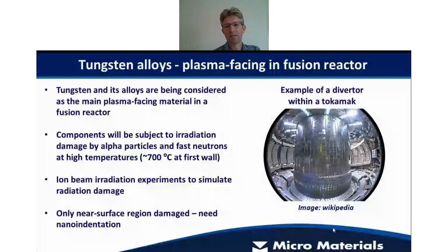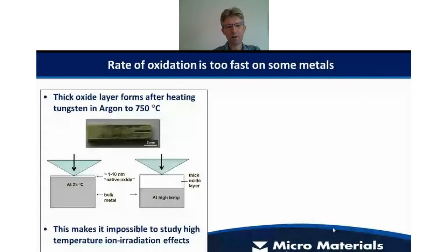So one particular application of this, and it's particularly timely now, since Tuesday the construction started on the ITER fusion reactor in the south of France, and tungsten has been used in these as a plasma facing material. And in this application, the tungsten components are subjected to irradiation damage, and a lot of research is based around trying to simulate that type of damage with ion beams. And in this case, the samples are not radioactive. The damage is restricted to a few microns within the surface, and we can test these in nano indenters. So it's a good way to simulate the radiation damage that is caused by alpha particles and fast neutrons.